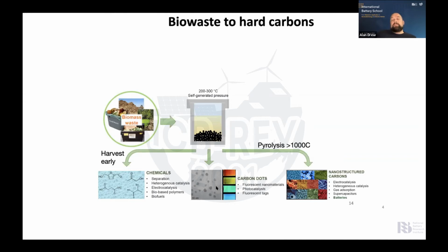You can also harvest at the end, and then you end up with carbon dots, which can be used as fluorescent nanomaterials and photocatalysis and things like that. And here are some pictures of different fluorescences depending on the size of the dots, depending on the conditions in here. Or you can pyrolyze them at greater than 1,000 degrees C and end up with a whole host of different structures, which then can be used as electrocatalysis or gas adsorption, supercaps, batteries.